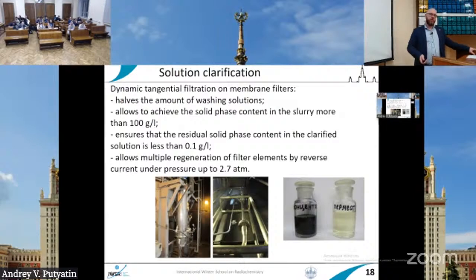So it allows to concentrate these particles, these suspensions from the solution, up to the slurry with the concentration of up to 100 gram per liter. And the rest of the solution contains less than 0.1 gram per liter of the solid particles. So it is an example from the test operation of this equipment. So after the filtration, it is the concentrate, so this slurry, and it is the solution that goes for the further reprocessing.